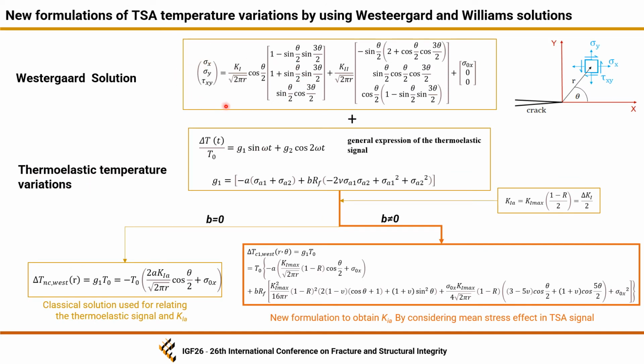So, by considering the Westergaard solution, where we consider the presence of T stress, and by coupling this equation in the general expression of the thermoelastic signal as previously seen, we can see the new formulation if we consider that the B constant is different from 0. In case we have B equal to 0, we have the classical solution used for relating the thermoelastic signal and stress intensity factor.